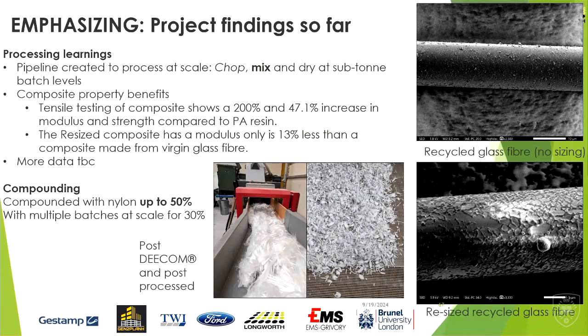And so far, we've shown that we can recompound this material after resizing, we can put it up to 50%, and we can also show that we get a tensile benefit of including this material. Naturally, glass fibres can be quite sensitive to heat. So we are reducing the temperature compared to some other methods. And so while we get some knockdown, it's less than you'd expect.